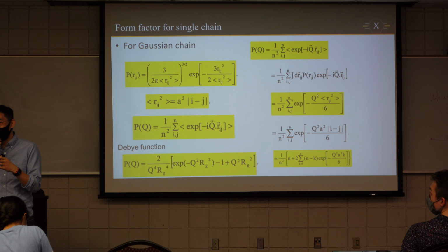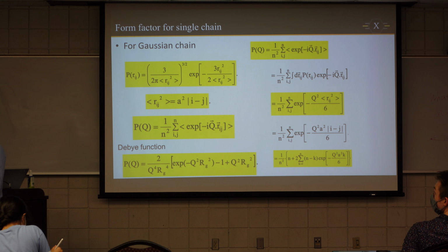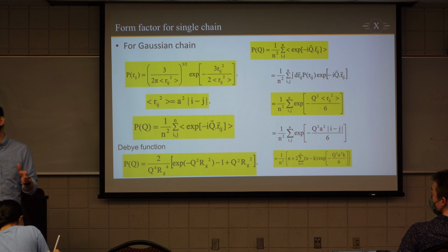But at low Q, you can think about a filter on your film, a mosaic filter. You just filter out, and everything gets fuzzy because you don't have the power to resolve everything inside. A porous particle actually has no difference from a solid piece of particle with an averaged scattering length density for your porous material, right? Think about air effectively lowering the electron density.